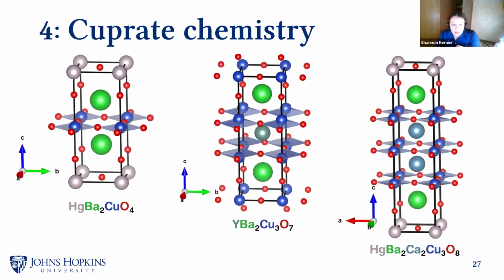Okay. For our last case study, we wanted to talk about superconductors, specifically the cuprates. They're really, really well-studied superconductors. And in the cuprates, the whole field as a whole has found that there are two important factors that you can tune that will help to control the superconducting transition temperature, which is the temperature to which you must cool your material before its resistance drops to 0 and it becomes a superconductor. And those two factors are copper oxide planes, which I've denoted here with these diamond-shaped blue lines, and the spacing between them in your unit cell.